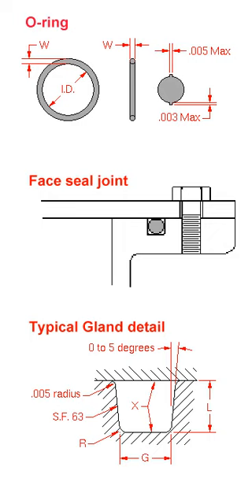Fluorosilicone has a somewhat more restricted temperature range. Additional materials include styrene butadiene rubber, thermoplastic elastomers, and thermoplastic polyurethane TPU. Polyurethanes differ from classic elastomers in that they have much better mechanical properties, including high resistance to abrasion, wear and extrusion, high tensile strength and excellent tear resistance. Polyurethanes are generally resistant to aging and ozone, mineral oils and greases, silicone oils and greases, non-flammable hydraulic fluids HFA and HFB, water up to 50 degrees Celsius and aliphatic hydrocarbons.